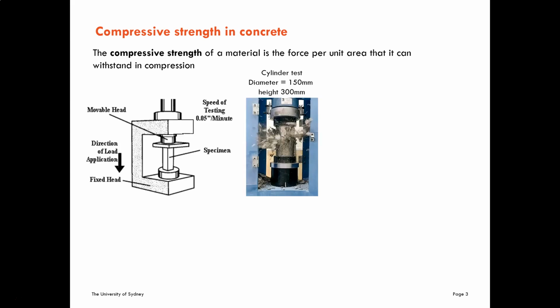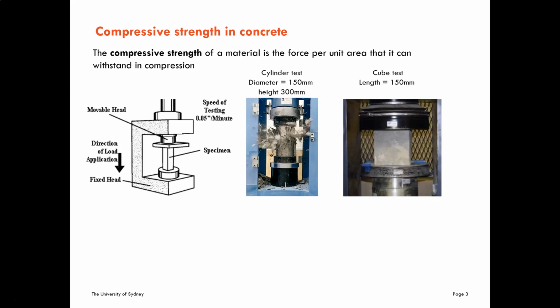So this is one example of the test. This is with the cylindrical test, but you can also have a cubic test. This is a typical stress-strain behavior, where you can see here that the stiffness is reduced, indicating some yielding or plastic deformations. It's going to reach a point when the material cannot sustain any more stress, and this is going to be the failure point. So in this case, of compression, it corresponds to the compressive strength of the concrete.